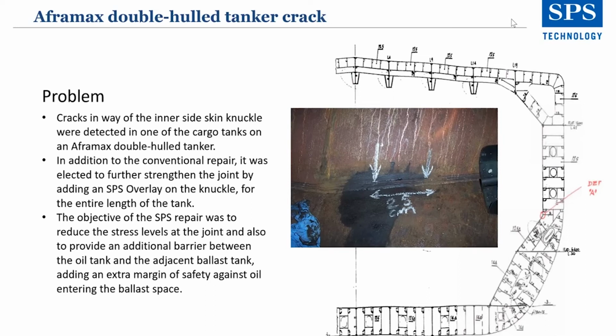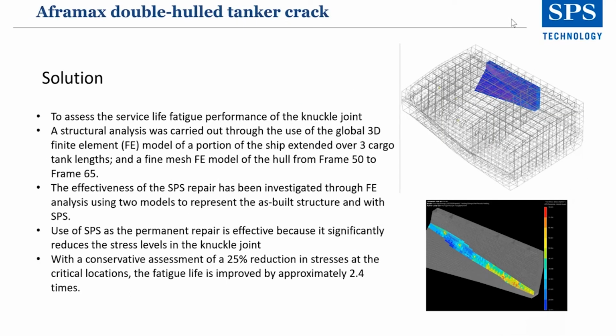So the solution to assess the service life fatigue performance of the knuckle joint, the structure analysis was carried out. The effectiveness of the SPS repair was investigated through finite element analysis, using two models to represent the as-built structure with SPS. The use of SPS as a permanent repair is effective because it reduces the stress levels at the knuckle joint, with a conservative assessment of 25% reduction in stresses at critical locations. So the fatigue life is improved by approximately 2.4 times.